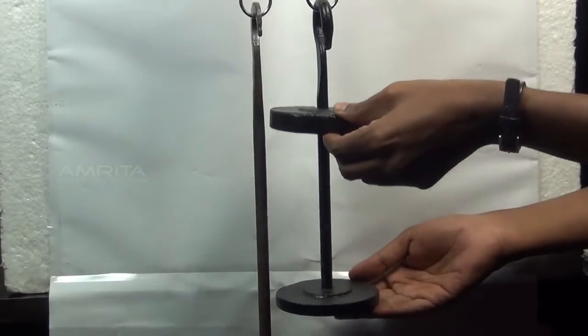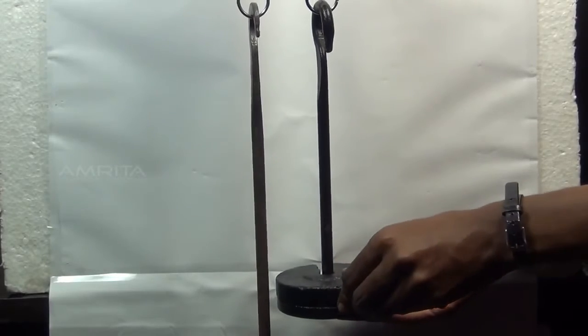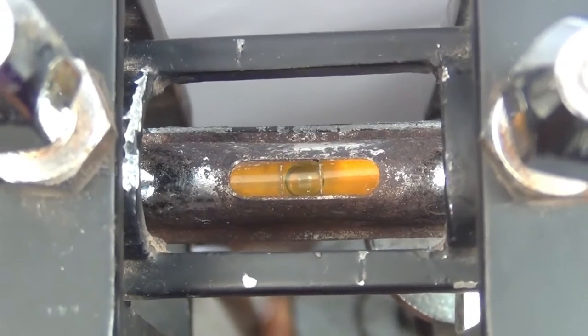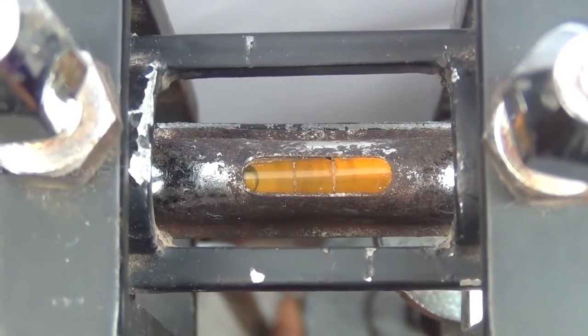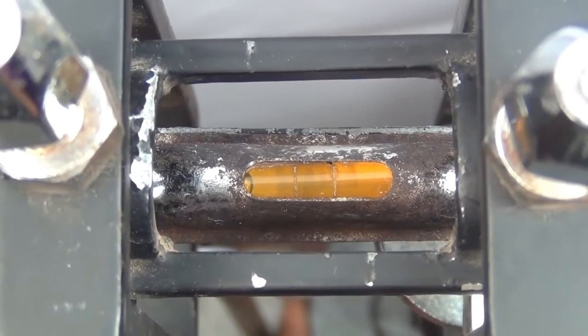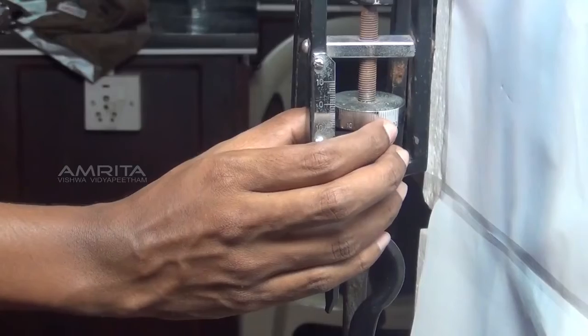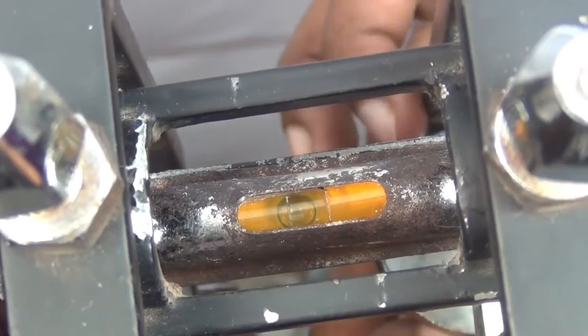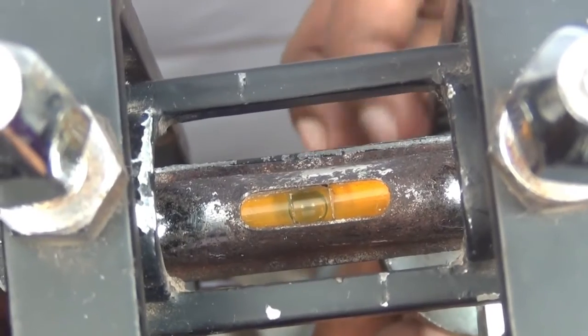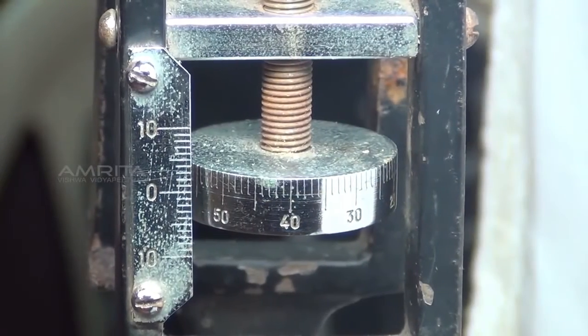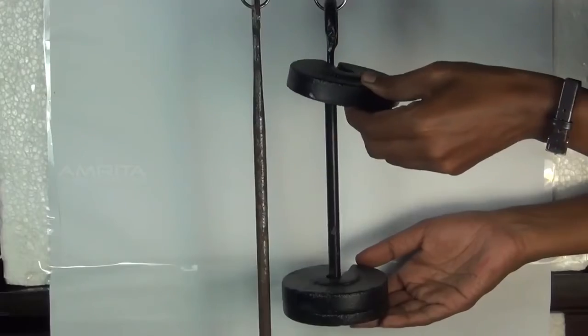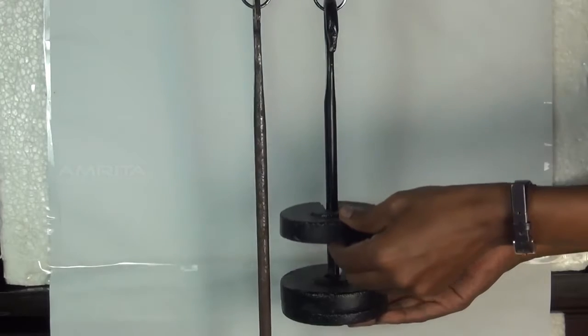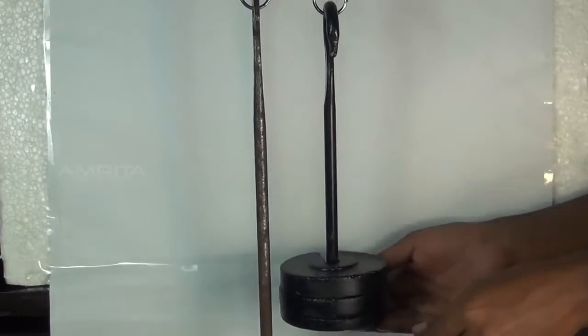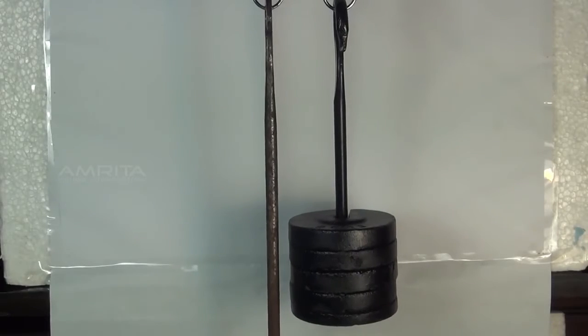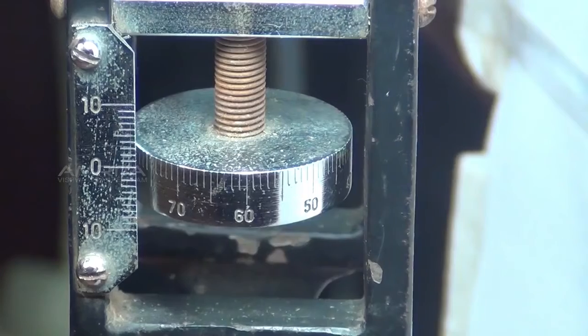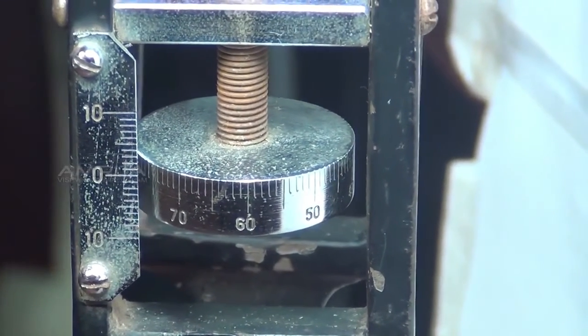Add 0.5 kilograms weight to the weight hanger. Now, the wire extends and the bubble is then shifted to the left due to greater weight on the right side. Adjust the central screw again to make the bubble at the center and note the corresponding spherometer reading. We can repeat the above process by adding weights to the weight hanger in equal steps of 0.5 kilogram. Note the reading in each case.